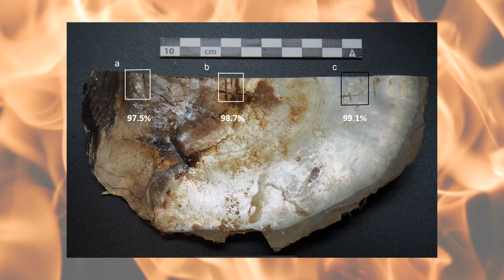I think anyone who's worked with shell a lot and transformed shell a lot knows often what you see is not what you get, and things can be quite transformed, yet not appear so visually. And recrystallized shell is potentially very problematic for radiocarbon dating, for stable isotope analysis. So it's important to check using something beyond your two eyes to see whether shell has recrystallized or transformed in